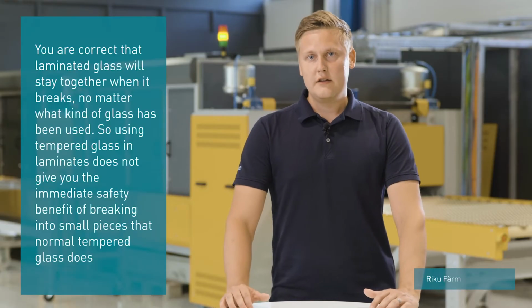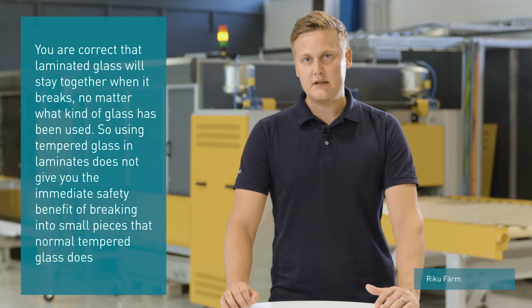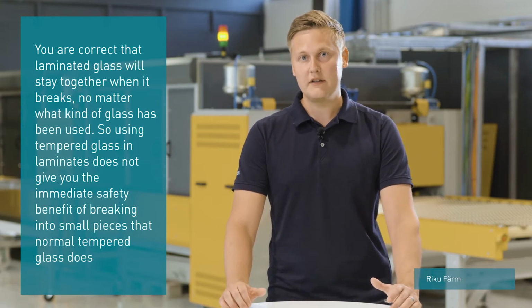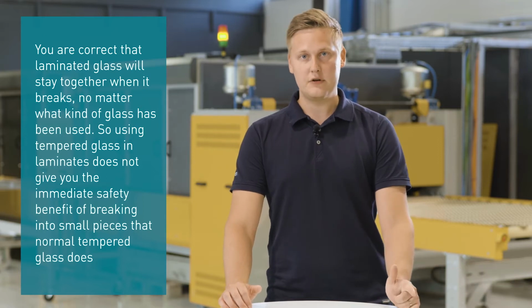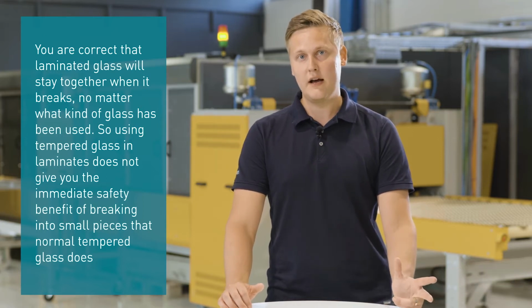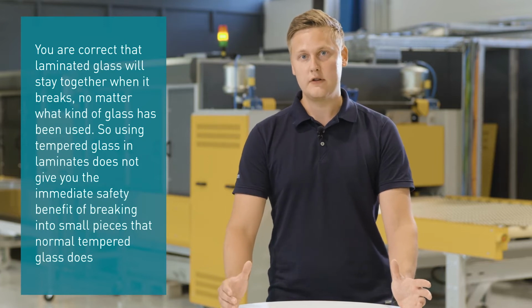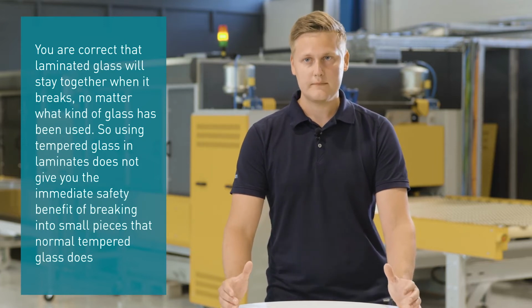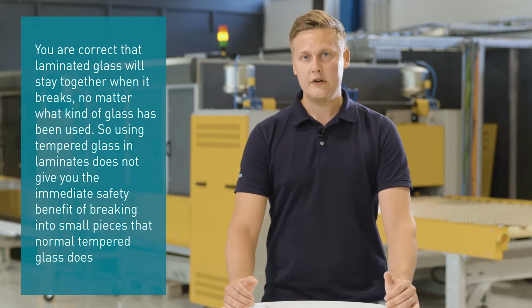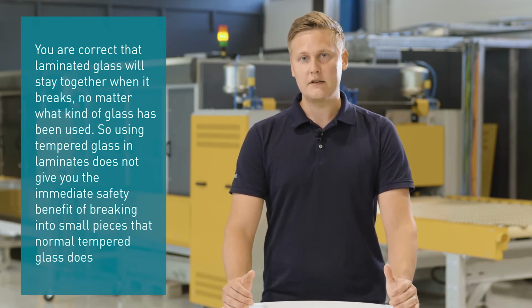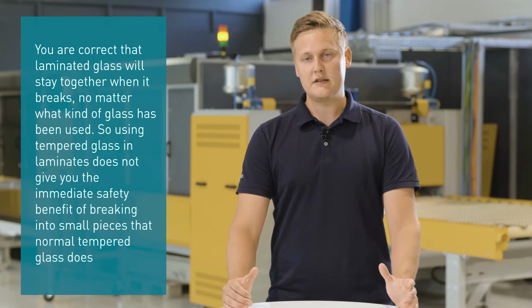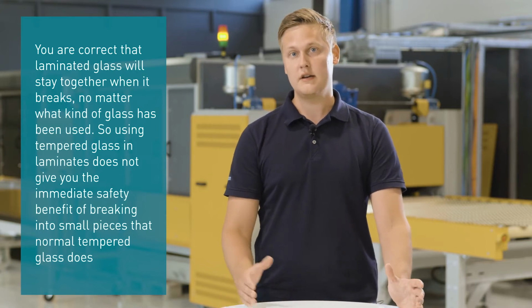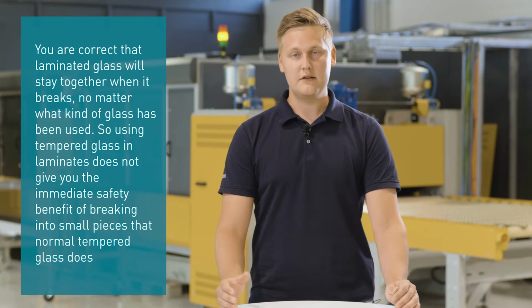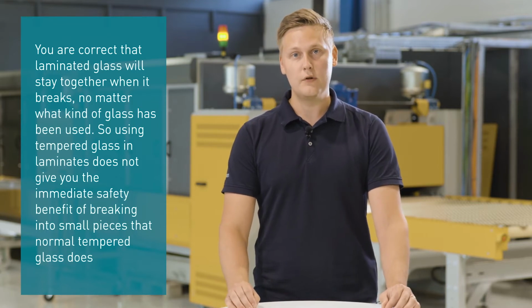You're completely correct that using laminated glass as a safety glass is not dependent on what kind of glass you have in the laminate. So whether it's an annealed glass, tempered glass, or for example a heat strengthened glass, it will still stick to the interlayer if something breaks. And that's a good point, that when you're using tempered glass in laminated glass, you don't gain the immediate safety effect that you do in single tempered units, where the glass breaks into smaller pieces and is not as harmful to people if it would break.